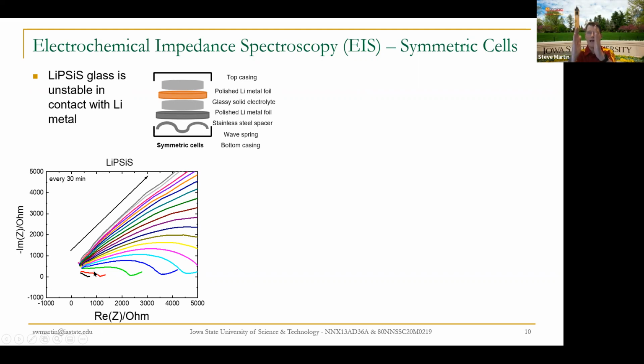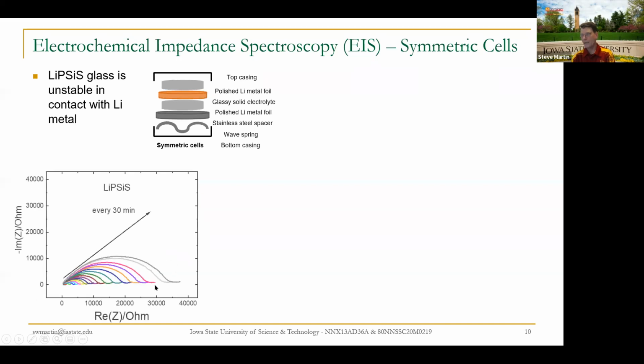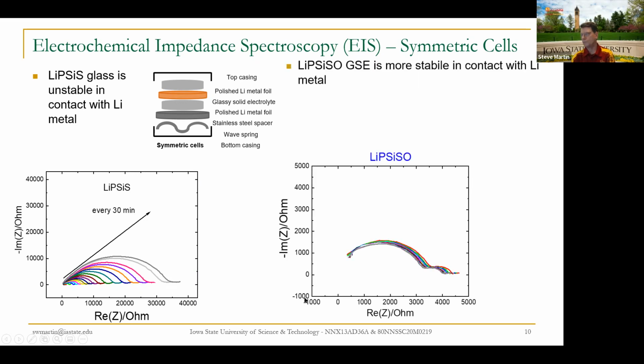You can just think of the glass reacting with lithium and forming an interfacial layer. It's like oxygen forming alumina on aluminum. It's like oxygen forming iron oxide rust on iron metal. And that barrier, of course, increases the resistance dramatically with time. I show that here. You start off with a couple hundred ohms and after only 24 hours you end up with 30,000 or so ohms, very high impedance, which makes the glass battery completely unusable.